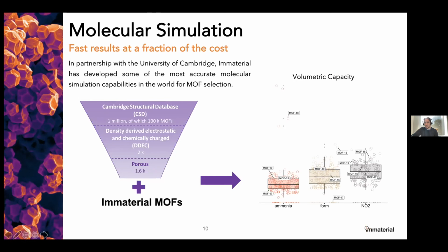Then we add in some of the in-house material structures that we've been working with predominantly, and run grand canonical Monte Carlo simulations on that data set against these specific pollutants. So as I mentioned previously, we're particularly interested in ammonia, formaldehyde, and NO2. And here, the spread on the x-axis is just to distribute the points. We've really just plotted those against volumetric capacity. The absolute readings that we get from these simulations on volumetric capacity, we found that sometimes they can be quite well matched to what we get experimentally. Other times they can be a bit off, but the ordering is consistently predictive of the right structures for us to be looking after. So order is probably more important than the absolute capacities of these.